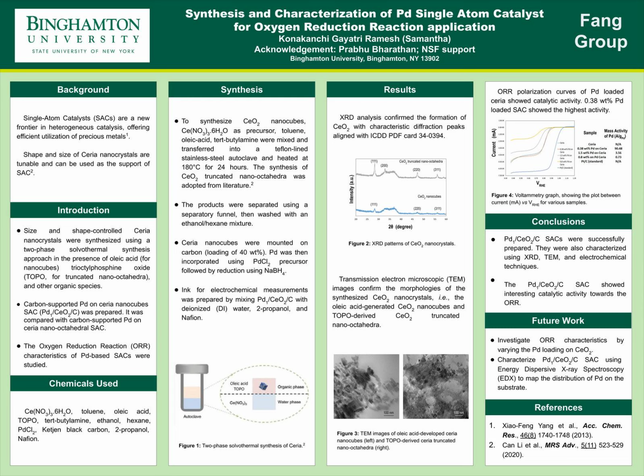The catalytic activity of the palladium single atom catalyst was studied using linear sweep voltammetry. Figure 4 shows the ORR polarization curves of four different palladium loadings on CeO2. As you can see, the catalyst with 0.38% by weight palladium loading showed the highest catalytic activity, indicating that this single atom catalyst has the potential to be an efficient electrocatalyst for ORR.